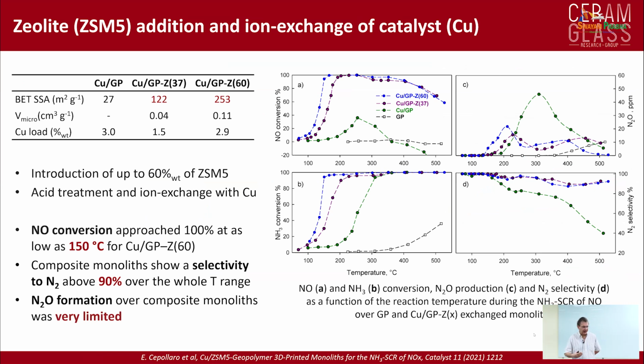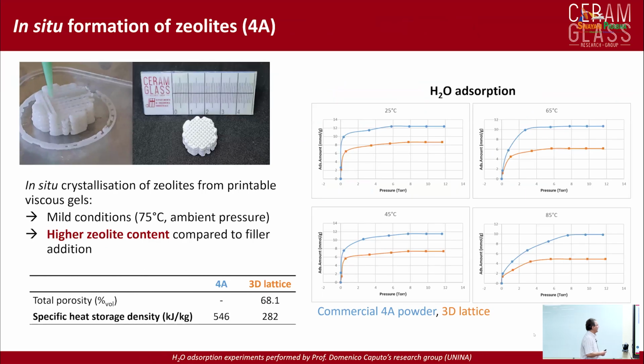This is one of the zeolites that can remain stable inside the material. With 60% zeolite, we can go up to 250 square meters per gram. We carried out acid treatment and ion exchange of the sodium ions in the zeolite with copper. And we looked at the NO conversion, nitric oxide, and at temperatures as low as 150, we were able to reach a conversion of 100% with a very good selectivity. So this approach is nice.